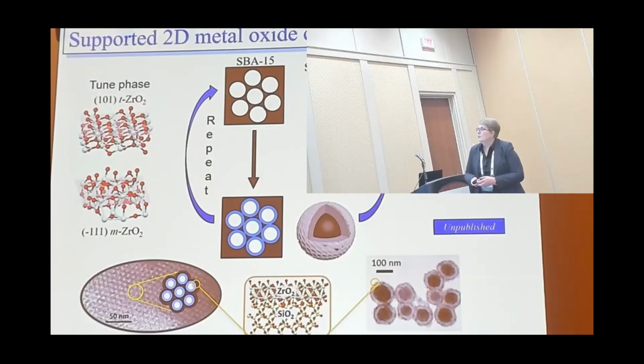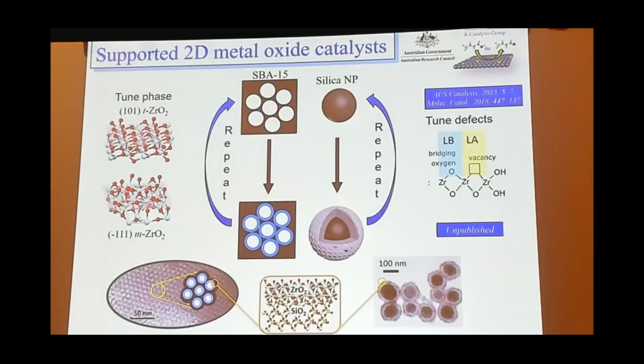Zirconia is also very flexible in terms of the range of phases that are accessible. And this actually opens up unique chemistry in terms of acid-base properties on the surface of these tetragonal or monoclinic zirconia surfaces. Your acid-base strength and distribution will be different. This comes from the production of vacancies in the surface. So if you have, for example, a defect that might be a Lewis acid site, the adjacent O2- in that bridge would be a Lewis base site. So it can open up cooperative catalysis between the base and acid sites in the metal oxide.